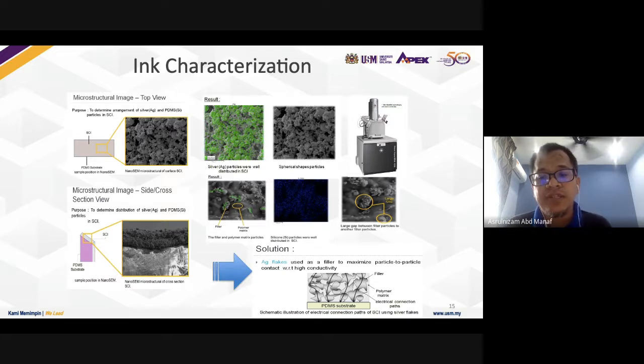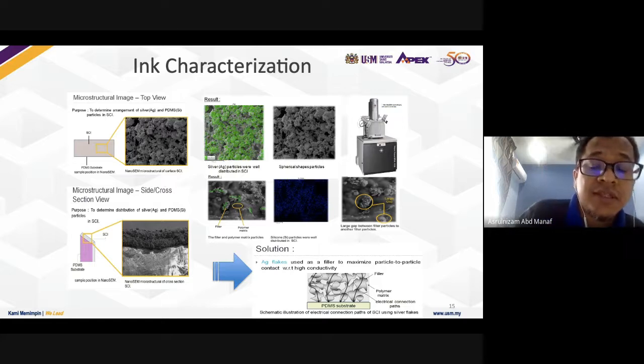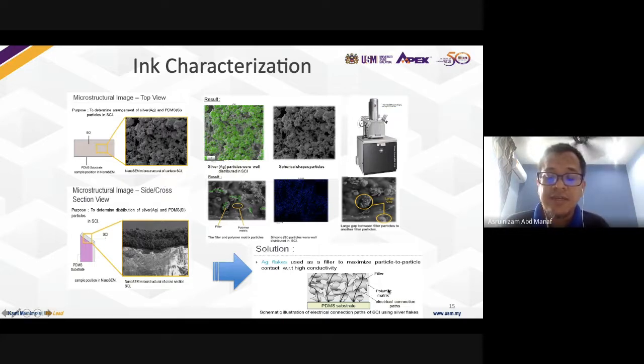That means there is a large gap between the flake and between the particles and the other particles. So if we can reduce the gap, you can improve the conductivity. At that time, they did some mixing to reduce the gap. They changed the silver nanoparticles to silver flake, and that can minimize the particle-to-particle contact. That was the development of a stretchable conductive ink using a polymer.